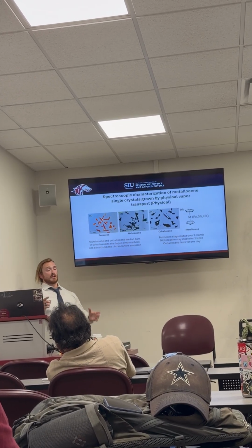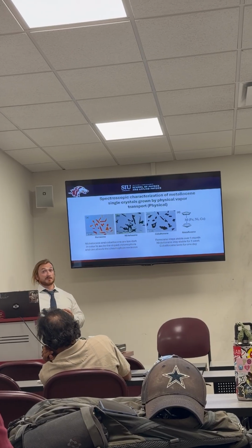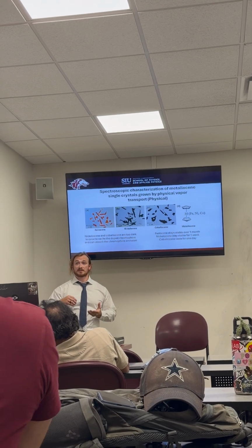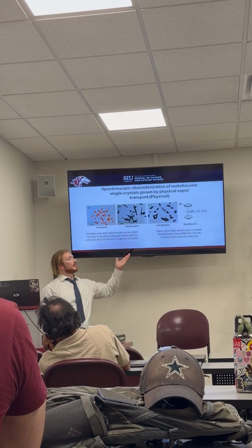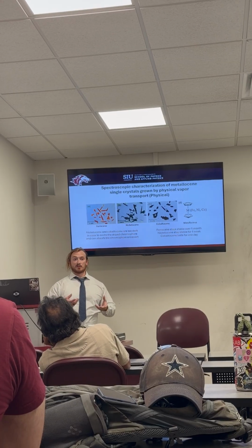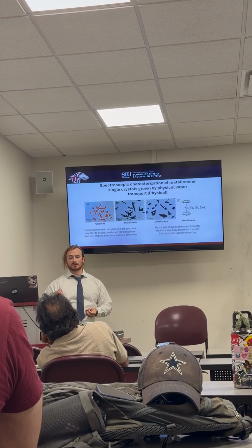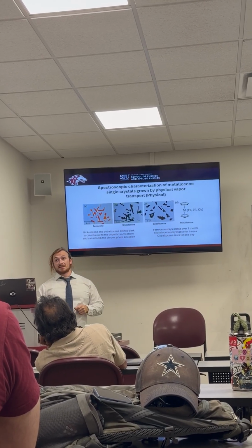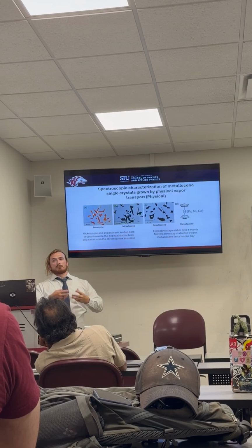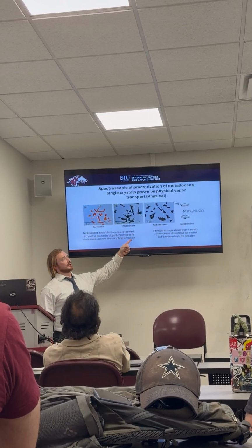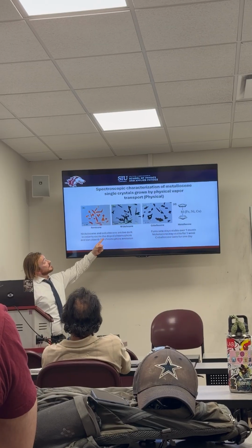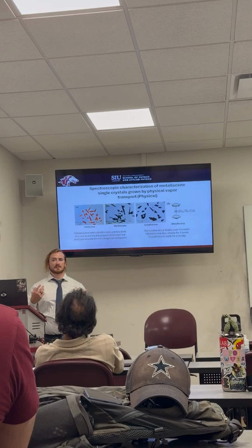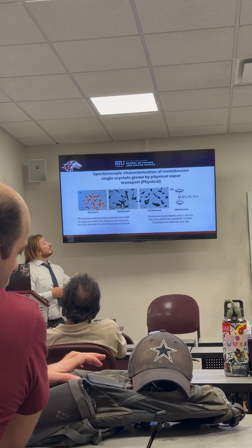Now, I said a chromophore absorbs energy and emits in the visible spectrum. Well, cobaltocene being nearly black, if you were to deposit some kind of chromophore in this material, it'd be hard to excite because the cobaltocene will absorb the excitation energy. If somehow it got inside the cobaltocene, the cobaltocene will reabsorb that energy. So in other words, this would not be a good emitter. Nickelocene suffers from the same kind of problem. It's a dark color. Although it's slightly translucent, it has similar properties.